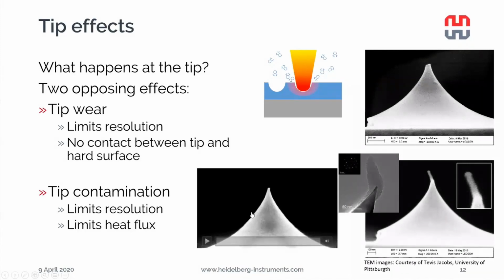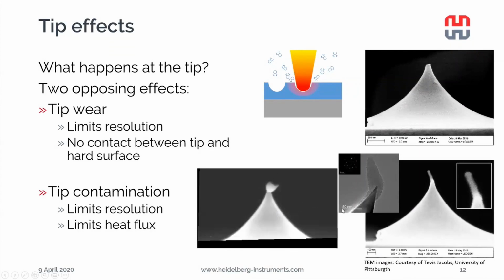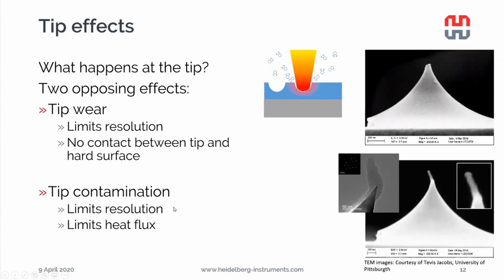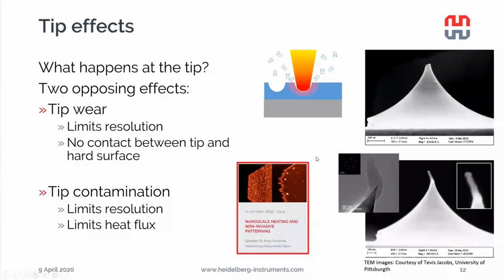transfer. Here we have an example where we did some SEM images of a tip in a quite fresh state. Then we did a lot of patterning, took it out, did an SEM image again, and observed these changes over time. We start with the fresh tip, then there's something growing, growing, growing, and even more growing. And this is one of the main challenges that we face with these tip and resist systems. This heat transfer has been covered a bit in more detail by my colleague Anja, and these past webinars will be online soon, I think, for all those that have missed them or want to look at them again.